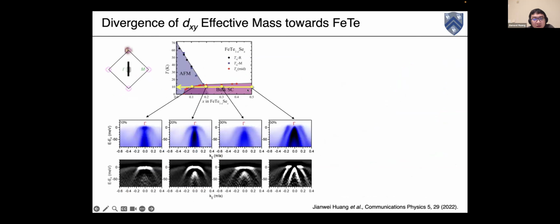So we took the ARPES data at several different dopings from the optimal doped FeTeSe to the iron tellurium end, and this is a gamma-M cut we observed, and this is second derivative data. Two things we find: one is that the bands corresponding to the YZ orbital, the effective mass does not change much with the different dopings, but the effective mass of the XY orbital is strongly enhanced towards the iron tellurium end.